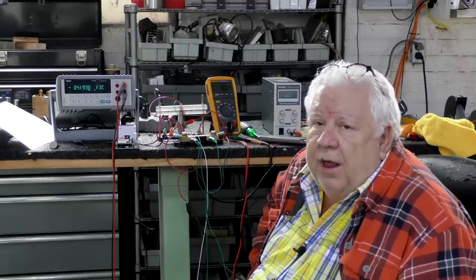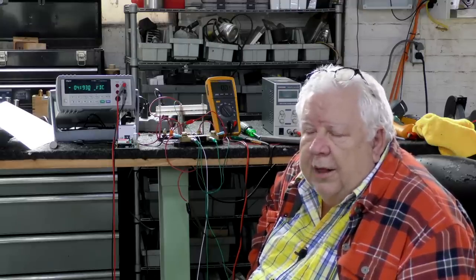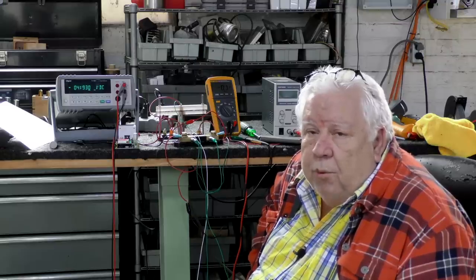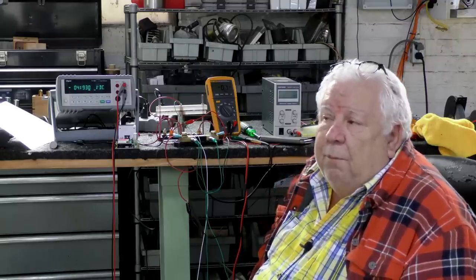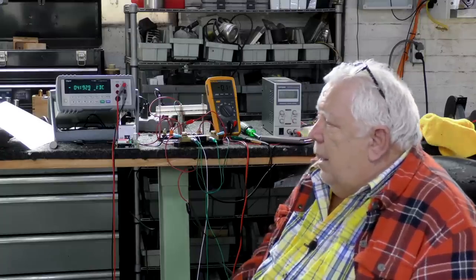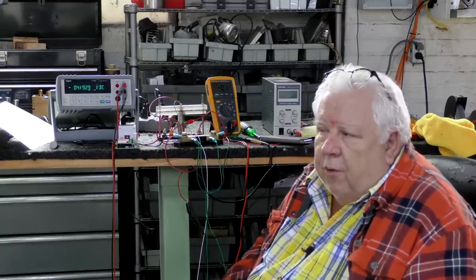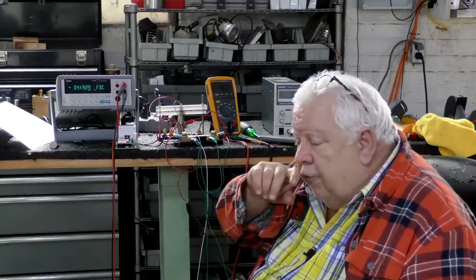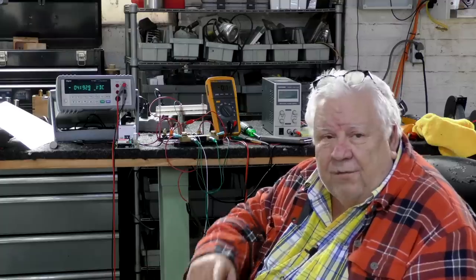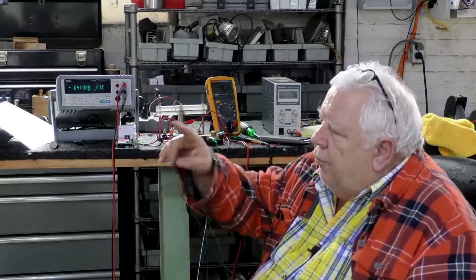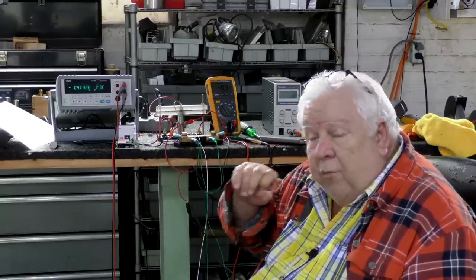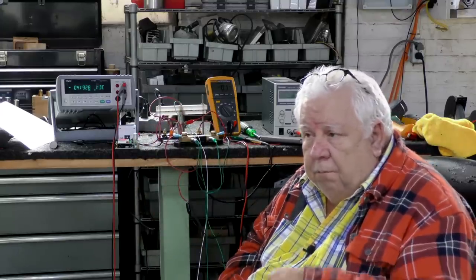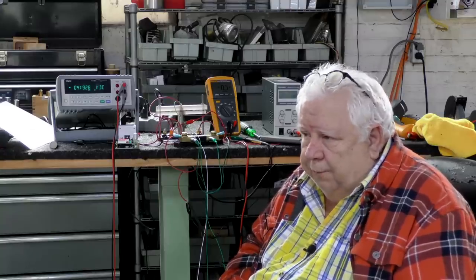If we do it at 5 amps or 1C, we're not going to get the same output of the battery. It would typically be less than we see at 0.1C. And so you have a series of curves of discharge at 0.1C, 0.25C, 0.5C, 0.75C, and 1C is typically a solid battery test. And those curves will vary with temperature, for one thing, but with this discharge rate primarily.